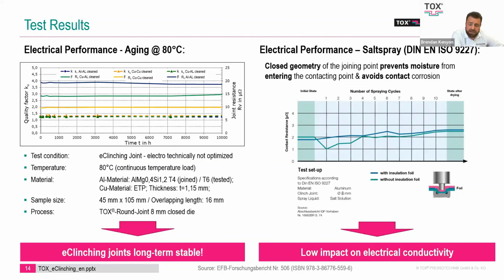But it's not uncommon for that joint to be as close, and in some cases it can be better, just because of that surface enlargement. You can have an excellent quality factor where the resistance in the joint is actually lower than the material, and that has to do with that surface enlargement. But yes, you can see here, you can end up getting long-term stable. So over time, any aging mechanisms, stress relaxation, electromigration, interdiffusion, grid deformation, whatever is happening over time, it can be combated by having that residual stress within the joint, and also not forming an intermetallic bond.